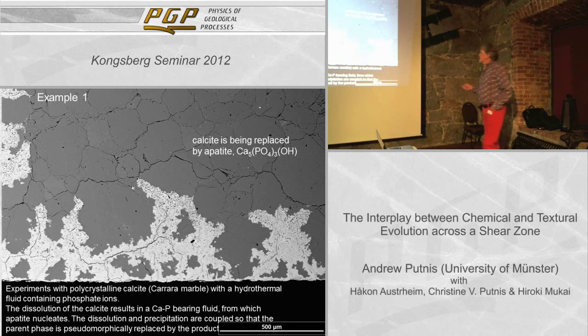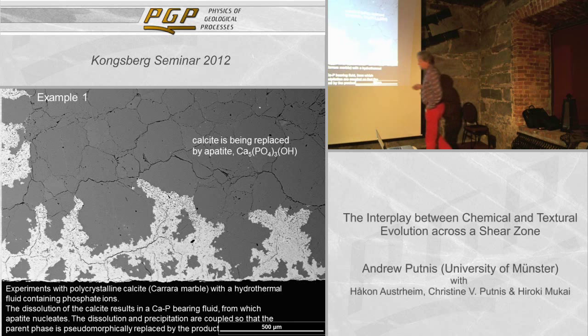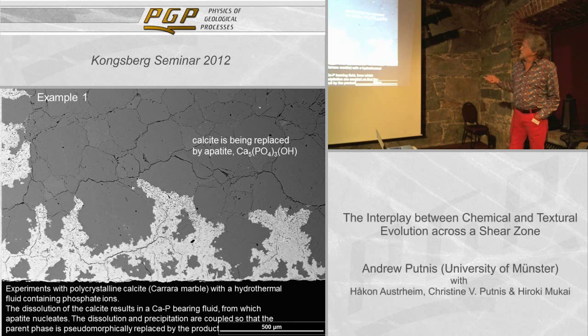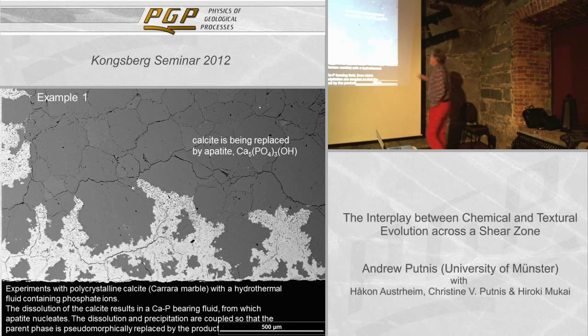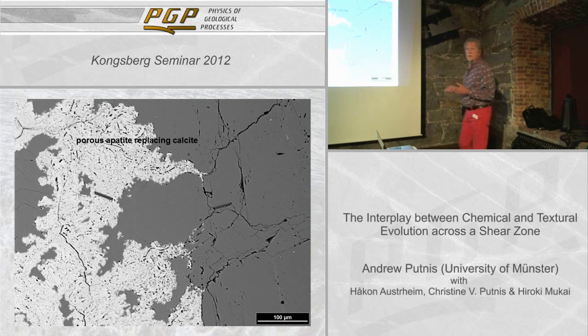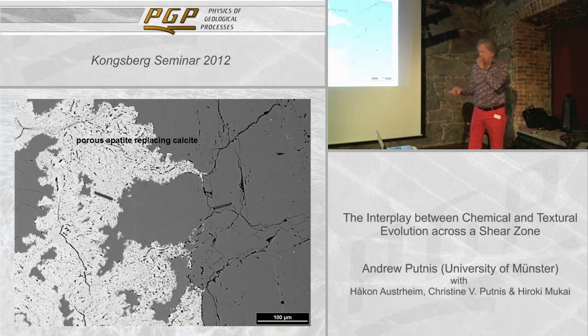So all this white stuff is apatite. It's an interesting experiment to see to what extent you get grain boundary migration of the fluid. We can do this with oxygen-18 — you can map the oxygen-18 from the fluid, and it actually goes into the phosphate of the apatite — you can track it with Raman spectroscopy. The other thing to point out is this is porous. If this wasn't porous — all these little black dots of porosity — this whole reaction couldn't proceed, because we have to have advective transport of fluid all the way to every point of reaction. Now, the porosity is a transient phenomenon — like any microstructure, it's transient, it might go away, it might coarsen, it will change with time.